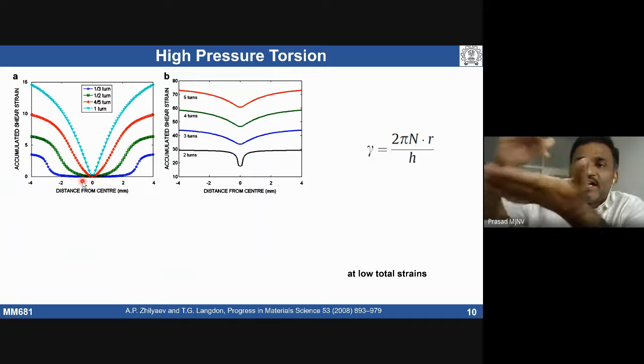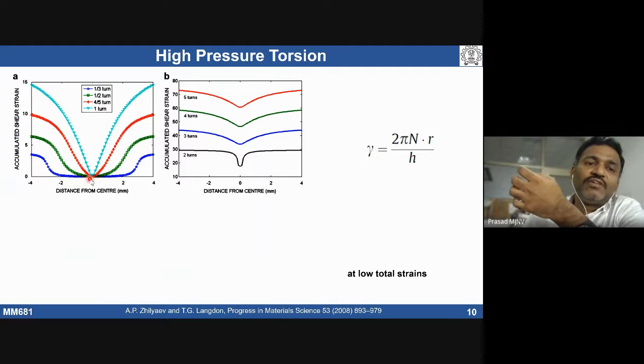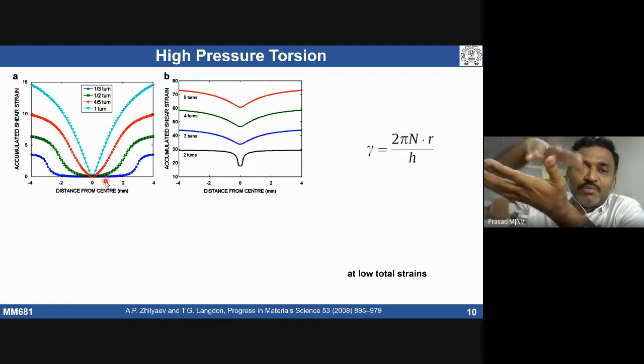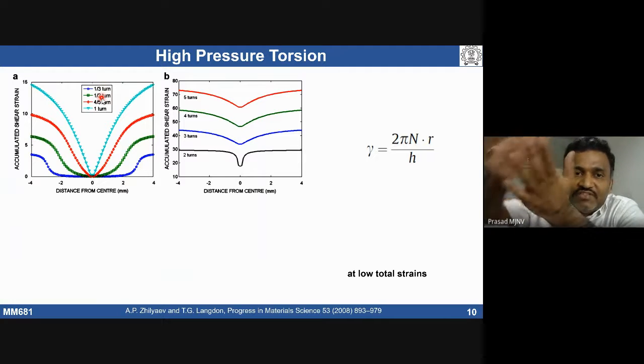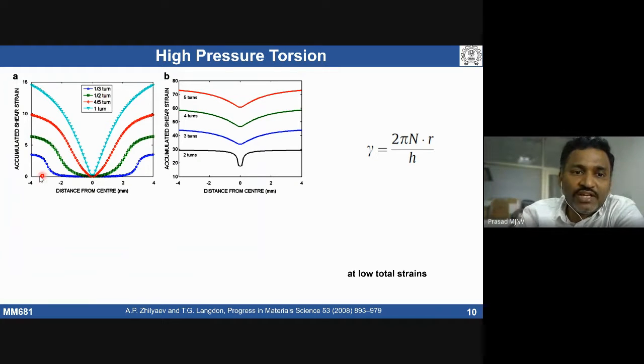If I take a disc, with the center of the disc at 0, and move towards the left or towards the right, that means towards the edge. Say this is an 8 mm diameter disc. From the center, depending on the number of turns, if you give one third turn or half turn, or 1 turn, look at how the strain is getting accumulated. The side edges of the disc have higher strain, and as you go towards the center the strain is lower, up to 1 turn. So with increasing turns, we see increased accumulated strain at the edge, and the accumulated strain increases with increasing number of turns.